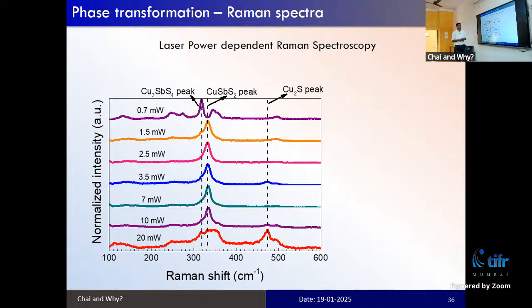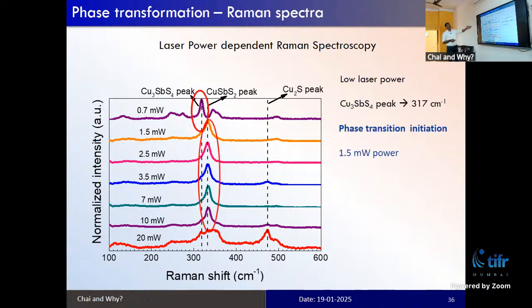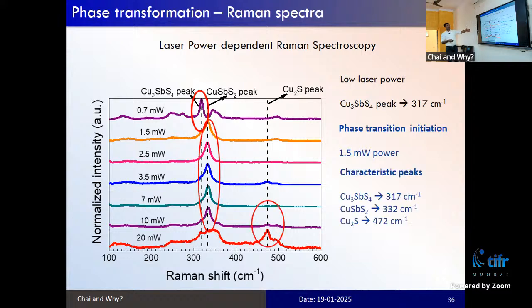What is happening? In the initial phase, at low power, you get the copper antimony sulfide, the famatinite phase, and when you increase the laser power, we get CuSbS2, a different stoichiometry, stable phase of copper antimony sulfide. So this is Cu3SbS4. There is a phase transition after 1.5 milliwatt power, and these peaks correspond to CuSbS2, and finally it transformed into Cu2S, copper sulfide.